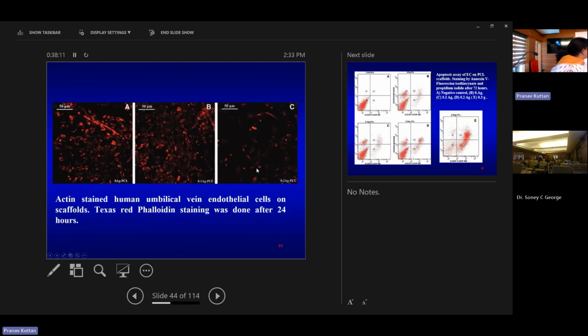So this is actually actin stained human umbilical vein endothelial cells on scaffolds. The first one has no silver, the second one has 0.1, and the third one has 0.2 silver. We can see that in the 1 and 2, the cell attachment is almost the same. That is, there is not much toxic effect seen. But as the concentration of silver increases, the cell spreading and attachment is less.